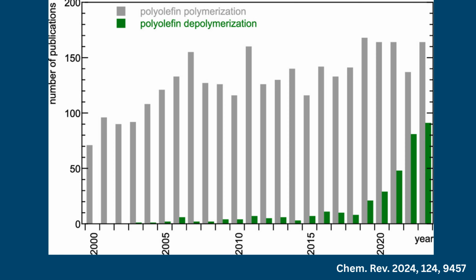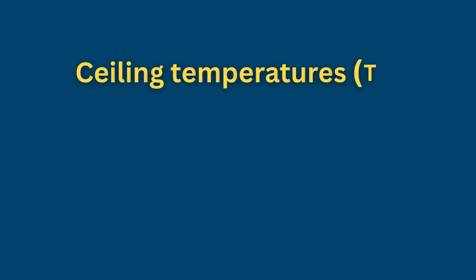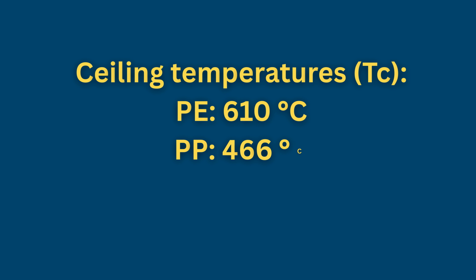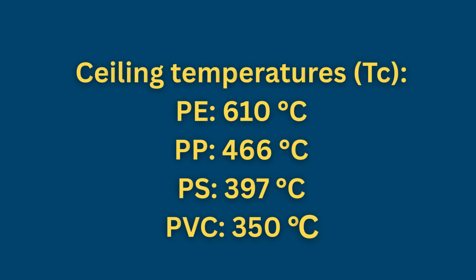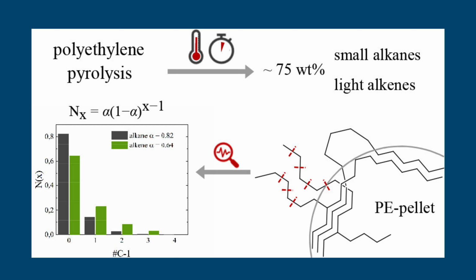Limitations of thermal depolymerization. Uncatalyzed depolymerization of polyolefins is thermodynamically feasible above their ceiling temperatures, Tc. However, these temperatures are high. PE, 610 degrees Celsius. PP, 466 degrees Celsius. PS, 397 degrees Celsius. PVC, 350 degrees Celsius. Before reaching Tc, polyolefins typically undergo unselective pyrolysis, greater than 500 degrees Celsius, producing complex mixtures of gases, low-grade liquids, and coke.